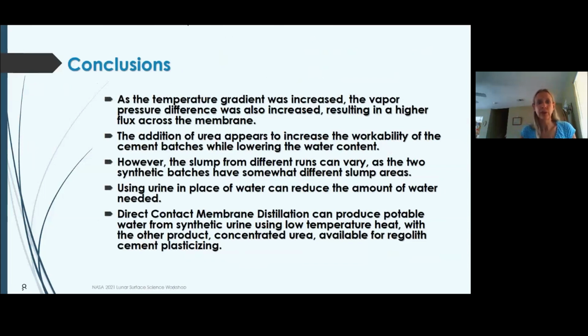And so in conclusion, obviously higher temperature, you have a higher vapor pressure difference, so you get more flux across the membrane. The addition of urea appeared to increase the workability of the cement batches. Although slump is not a very exact test, as you can imagine, you could still tell a difference between the two, having urea in there and not having urea in there, as in deionized water. If you were to use urine in place of water, you could reduce the amount of water you would need. And it also would produce potable water from urine using a relatively low temperature heat source.